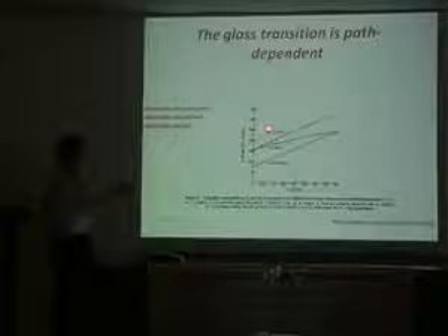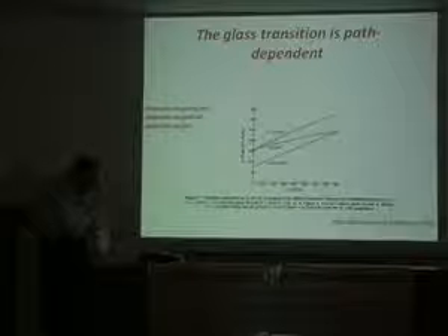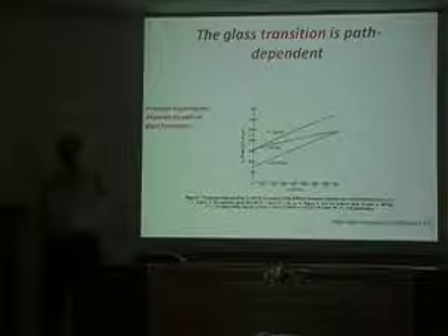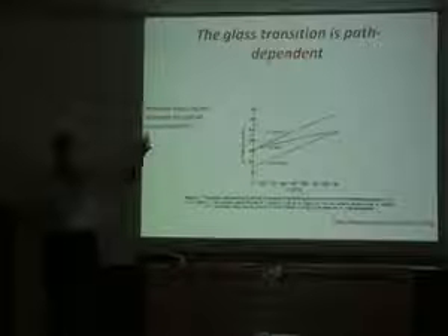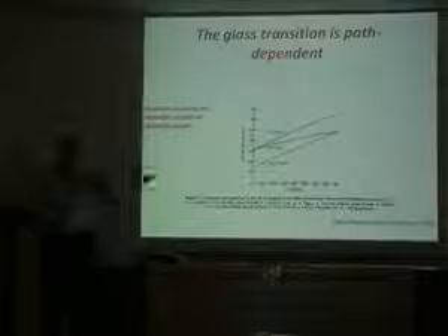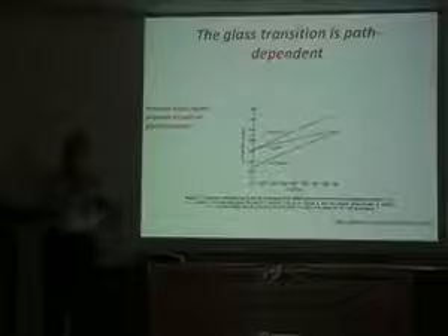Okay, here you pressurize in the liquid state, and at each pressure cool isobarically. Here they pressurize in the case of the P0, what he called in this one P and 0, that corresponds to this one. Okay, and then you pressurize. And he also had one where he formed it here and then depressurized. Okay. Those are the 3 curves, right? But the big thing is that's a detail. But the big thing is to realize that, of course, even the apparent strength of the transition in terms of dTg/dP is a function of how you did the experiment.